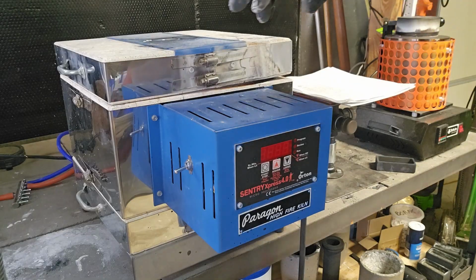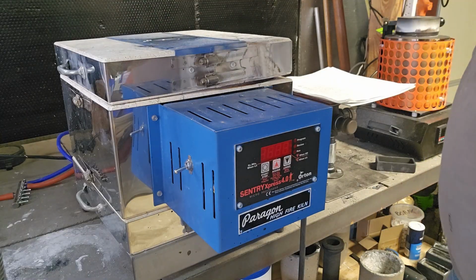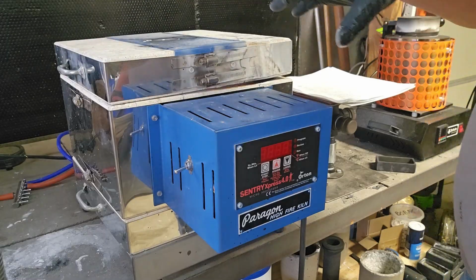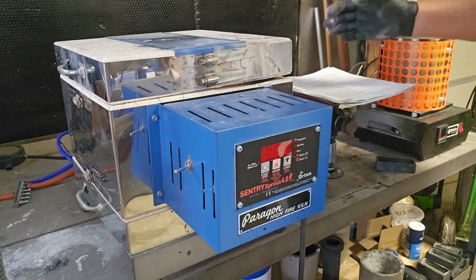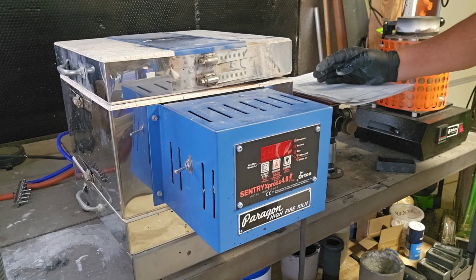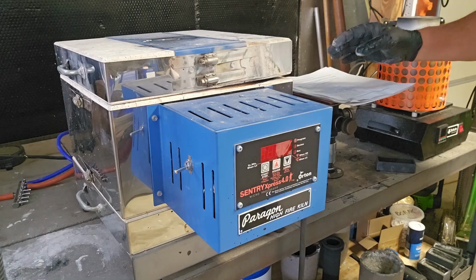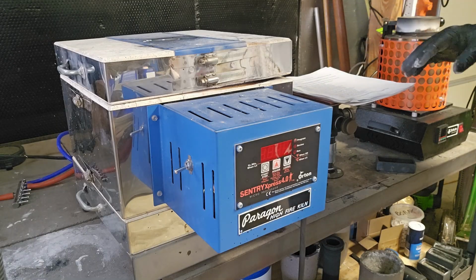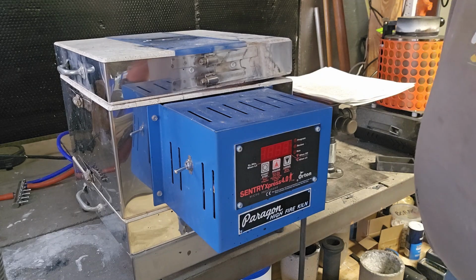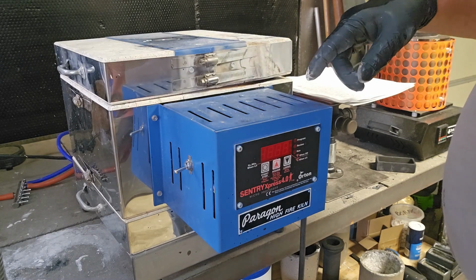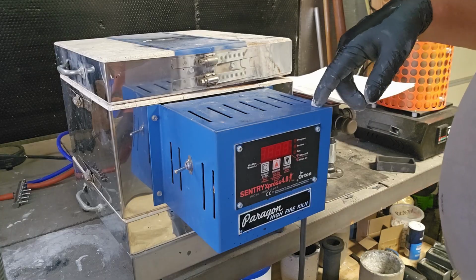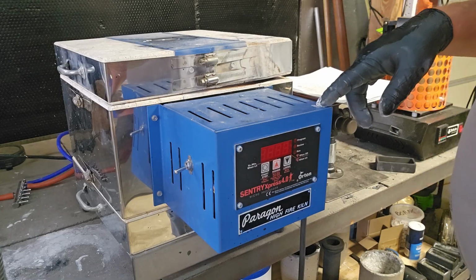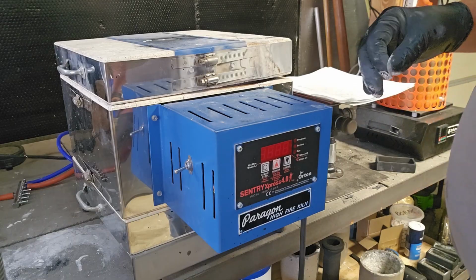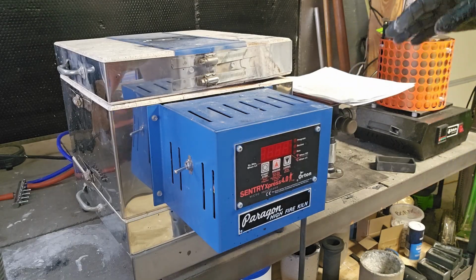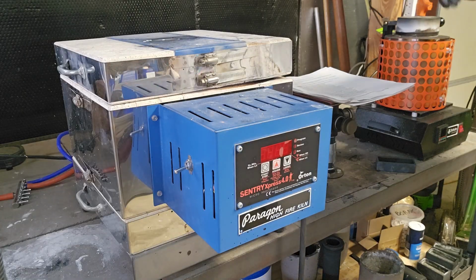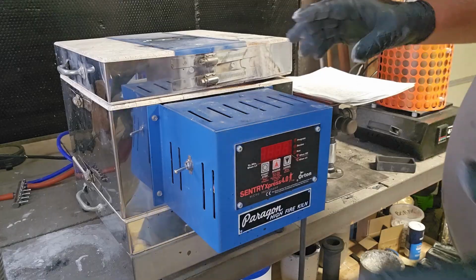Now what I usually do is I have it preheated to 500 degrees C, so when I take it out of this kiln and get ready to pour the molten aluminum into it, that can and plaster is 500 degrees C. So that's the sequence here. Now you got to time this, so I'm going to tell it to start at 7 p.m. tonight, so that by 10 a.m. tomorrow is about the time it'll be cooled down to where I can melt my aluminum and pour it in the mold. So that's how all that works.